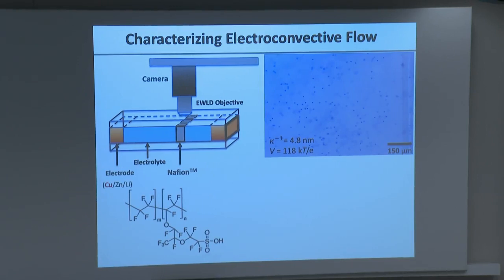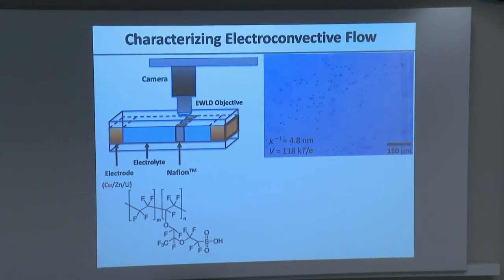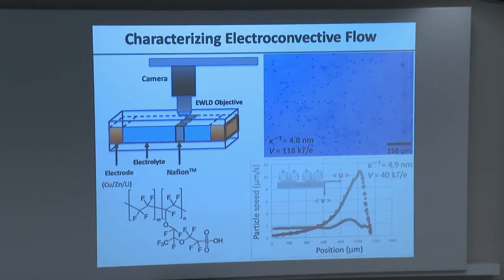And so the next click should give you a video of what we see, and there's nothing special here. And so if you look near the wall, you will see that all hell breaks loose in the fluid. And in fact, if you look at the structure of these rolls, you'll see that they're not dissimilar to what the theory says, indicating that indeed, this hydrodynamic instability predicted by simulations, this roll cell instability can produce convection and can produce highly localized convection, which can lead to the instability in the high current case that I mentioned earlier. So that was good. Now we can do more.